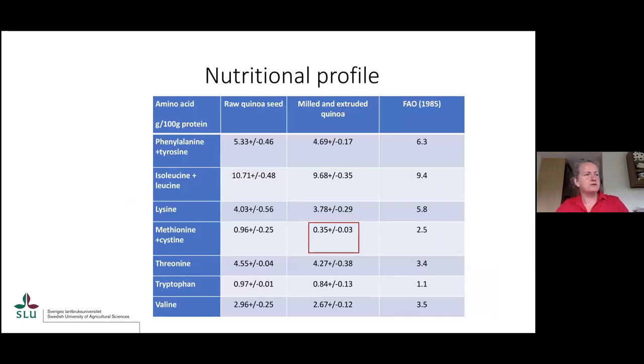From the nutritional profile, one of the questions is what is actually happening if we use high extrusion temperatures, and how the nutritional profile of this super cereal is affected. To our big surprise, only methionine and cysteine have been reduced, while other amino acids still kept quite good numbers after extrusion. I think it's important information to learn that you can still play with the processing and rather high temperatures, but you still don't severely affect the nutritional composition.